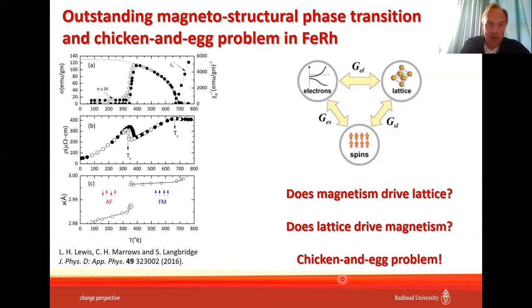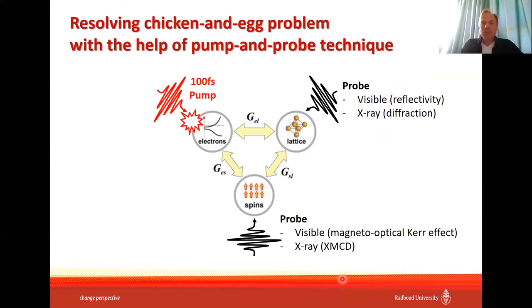But we are not the only ones who were excited about this material. And the first experiments which were performed, I think they dated already from 15 years ago. And the nice thing about this material is that if you excite it with, for instance, a 100 femtosecond laser pulse, it will excite electrons in this material. Why electrons? Because as we know, if we treat light matter interaction in the electric dipole approximation, we will be able to describe most of the effects observed in optics. So that's why we assume that light interacts mainly with electrons, puts energy into the electronic system,